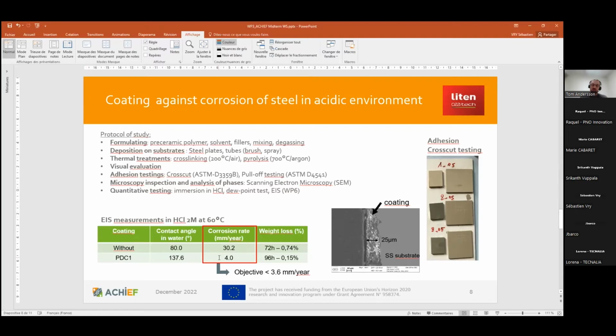At CEA, a dew point test bench was also developed. This bench allows us to put samples into an acidic gas environment, similar to the use case. Then we assess the performance of the coating by measuring weight loss and doing some microscopy.